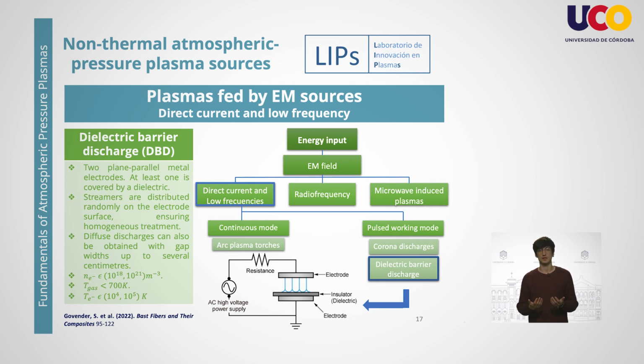treatment. Diffuse discharges can also be obtained in barrier discharge configuration at atmospheric pressure with a gap width up to several centimeters. In a diffuse configuration, the discharge is spread out over a larger area, typically across the dielectric surface. This is in contrast to filamentary discharge, where the plasma is concentrated in narrow filament-like structures. The diffuse configuration is often characterized by a more uniform distribution of the discharge across the dielectric material, leading to different plasma characteristics compared to filamentary discharges. This configuration is especially useful, for example, for the deposition of homogeneous thin layers on a desired material.